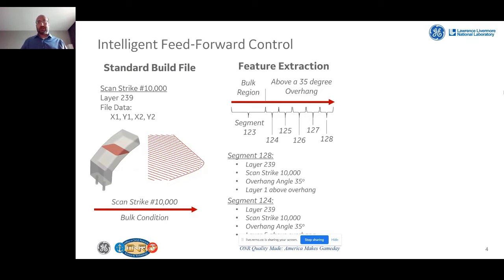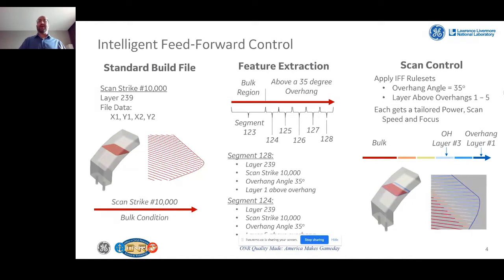Now, this type of demarcation of process variation along that laser strike then allows us to have more localized compensation and control to allow ourselves to have a more measured response to that change in process behavior. So taking that single laser strike that sees it going from a bulk region towards an overhang, we can now take that same laser strike, that same continuous movement of the laser, but now we can modulate the laser power or modulate the laser focus along that length, essentially create a gradient that steps us towards a more optimized scan strategy meant for an overhanging region of a part. And this allows us to have essentially no stops and starts, but it gives us a way to now have a smoother transition as we go between different features of parts and allows more tailored features as required for a part.